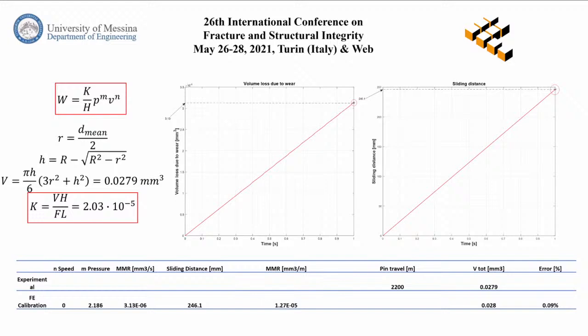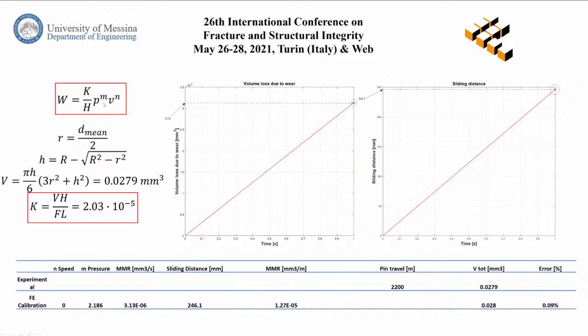This finite element method is used for the calibration of the Archard wear model, which is basically used for the evaluation of the wear process in general, for the volume loss due to wear for the contact between the acetabular cup and the femoral head of the prosthesis. So the calibration consists in the evaluation of the two exponents m and n of the Archard law. In particular, the model has four inputs. H is the hardness of the material, K is an adimensional constant called the Archard constant, and the two exponents are of the pressure and the speed respectively.